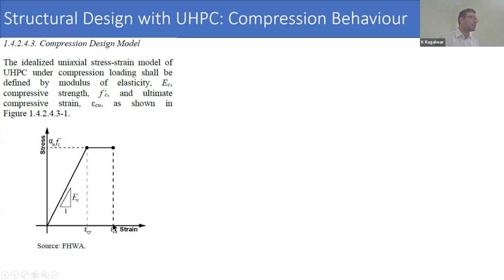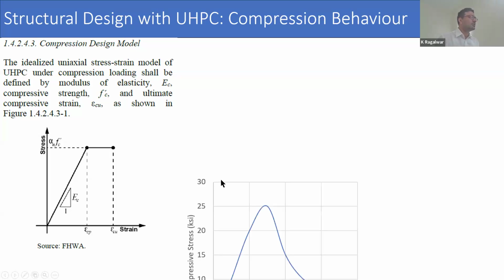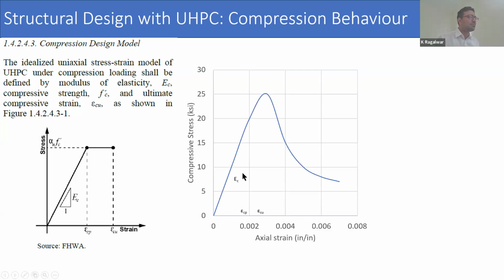limit of compressive strain. So if we look at this typical model, we first basically idealize the linear part of it. Then we determine what is the factored compressive strength, and then the strain related to that is the plastic limit. And then at the strain equivalent to crushing strain of concrete, we basically draw a horizontal line and cap it at that location.